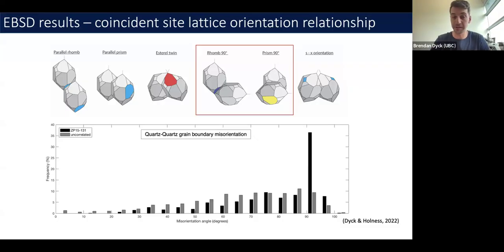Now, one thing that's missing from this data is we're not seeing anything to do with the parallel grains here, because of how the EBSD technique works, two parallel grains that meet together will be analyzed and indexed as a single grain. But we can get around that a little bit.